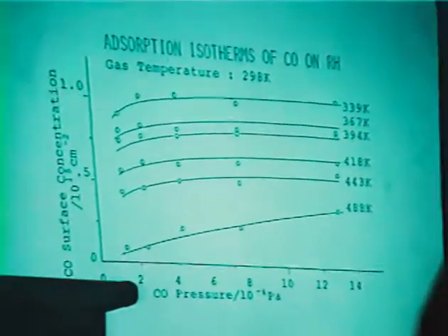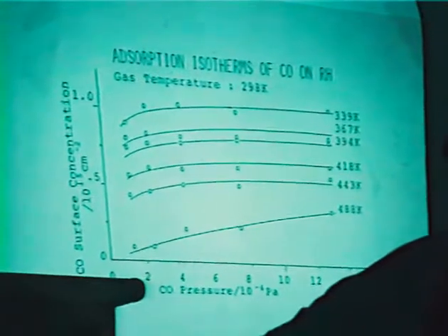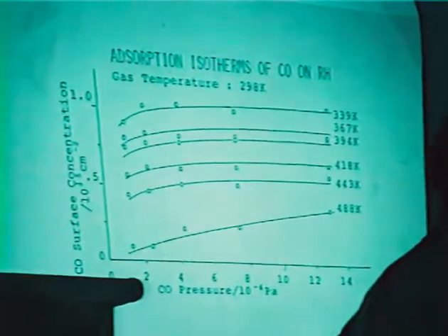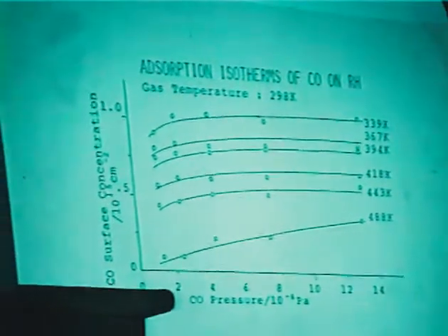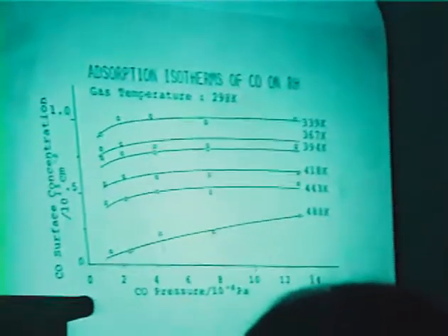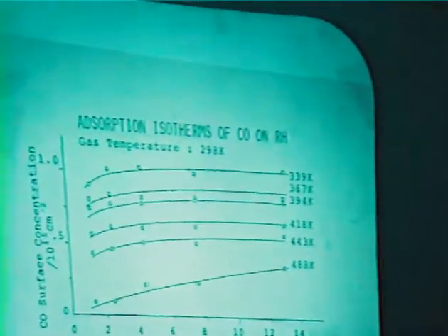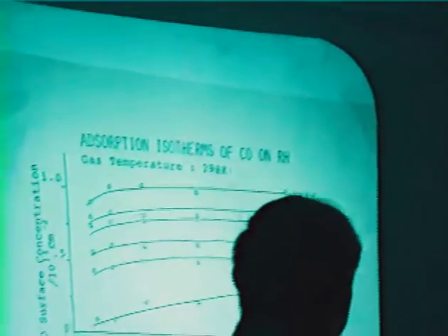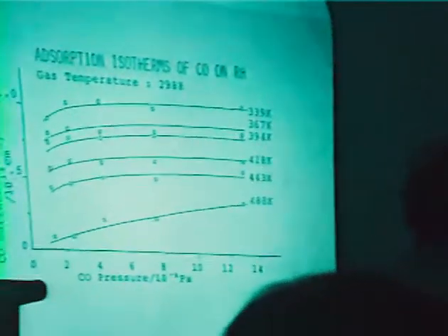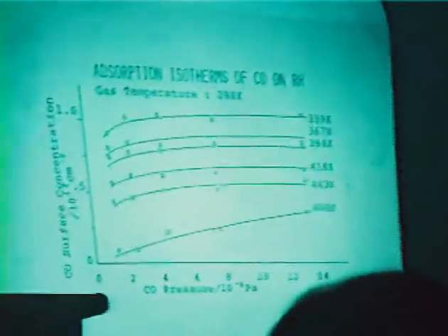And the saturation coverage looks to be dependent upon temperature, which is quite in agreement with the adsorption isotherm we have proposed. And at extremely high pressure, it will approach unity. But as you know, many people estimate the surface area of such catalyst surfaces by using pure CO approaches. But in some cases, we have to be careful to use such a technique on the basis of such behavior.